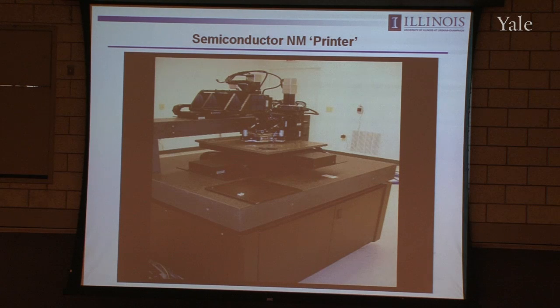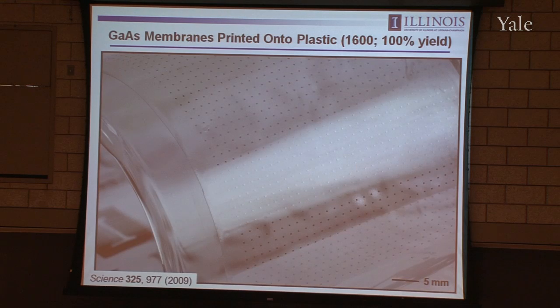We work with manufacturing engineers in our Department of Mechanical Engineering to build a tool like that. There's a stamp here. There's an inking pad. There's a processed wafer here. There's a two-axis stage that supports a platform here that corresponds to Gen 3 display glass. You can pick up membranes here using a stamp in this fixturing jig. There's a camera that allows you to look through the transparent stamp, so you can do registration and alignment, load cells over here, and it's all under computer control. So this can happen with very high throughputs, corresponding to about 1 million nanomembranes moved per hour with this kind of system, with very good overlay accuracy.